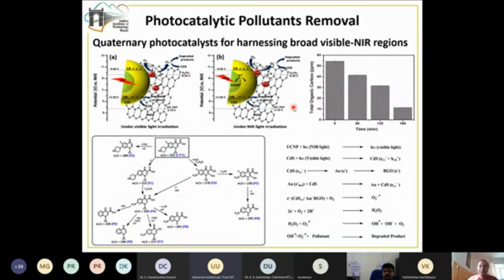Basically, if the light is from the visible light region, there is no role of the upconversion nanoparticle, and it's only the cadmium sulfide and the gold nanoparticles which are playing the role. The visible light is impinging on this material, which leads to the promotion of an electron from the valence band to the conduction band, which leads to the photocatalytic activity. The ciprofloxacin gets degraded into much smaller fragments.